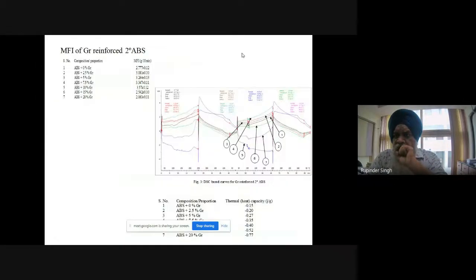We have reinforced ABS with graphene, right? So if you see, I have put the graphene into the ABS. As I am increasing the graphene proportion, I got a trend in the melt flow index. Similarly, I got a trend for its thermal capacity. Like with the reinforcement of the graphene, the thermal capacity is increasing. So it can absorb more heat in joule per gram.